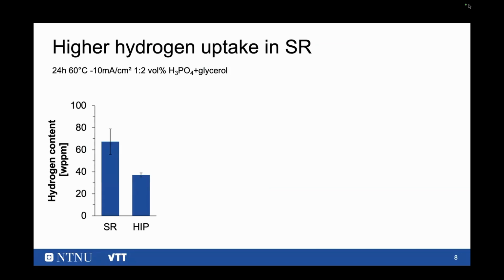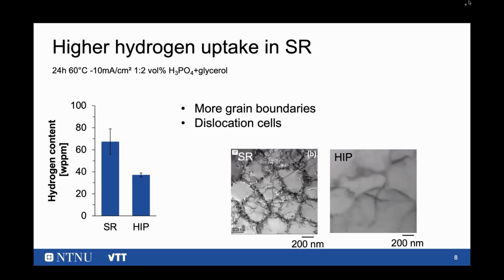So first of all, the hydrogen charging conditions: we always did galvanostatic charging at 60 degrees in a phosphoric acid with glycerol solution. And we see that the stress relief condition takes up definitely more hydrogen compared to the HIP condition. Although we should take into account that in this case the sample is not fully saturated yet, the main reasons that we see this trend are, on the one hand, that there are more grain boundaries present in the stress relief condition, but secondly also these dislocation cells play a role, because they serve as a kind of hydrogen highway to promote the hydrogen uptake and transport.